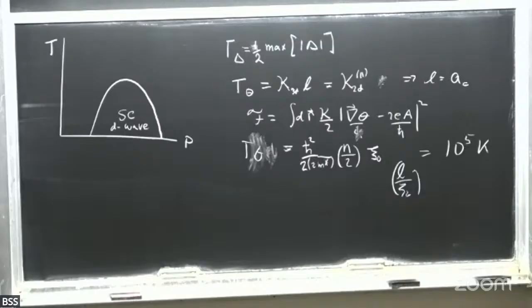Nothing. Because long before I reach that temperature, so this would be what Tc would be if the bosons had infinite integrity, if the binding energy of the electrons, rather than being the smallest energy scale in the problem, were the largest energy scale in the problem. So this is an upper bound on Tc. This is the temperature, roughly, beyond which only phase fluctuations would be sufficient to destroy superconductivity. But because it's so many orders of magnitude bigger than Tc, you know that this makes no difference in conventional superconductors.